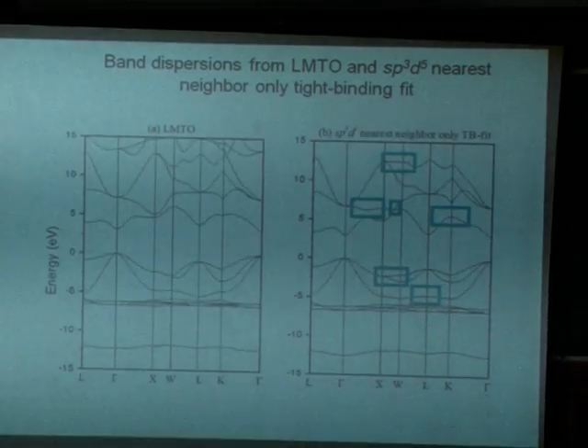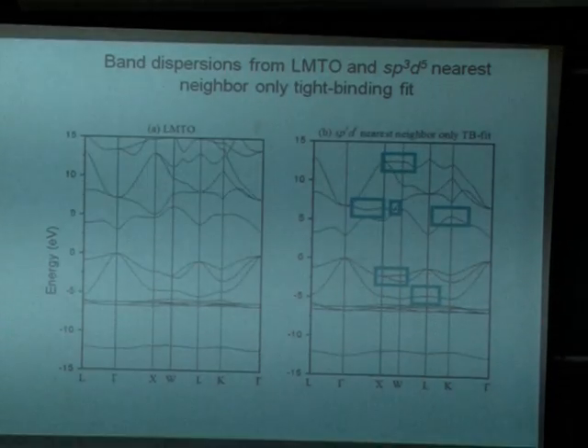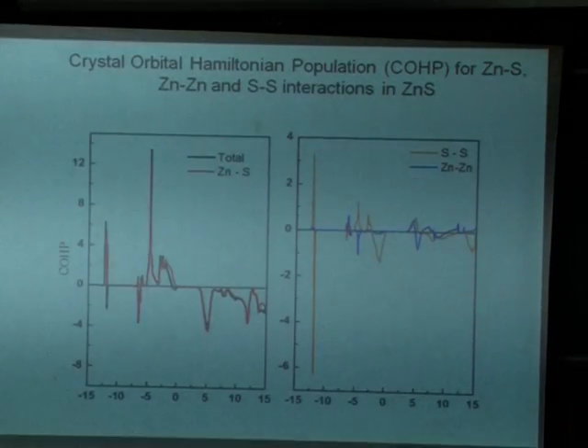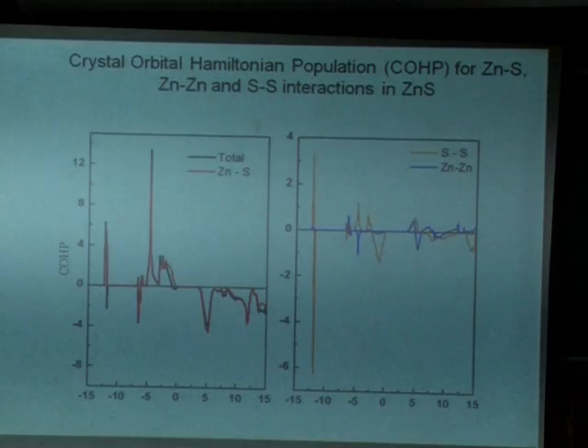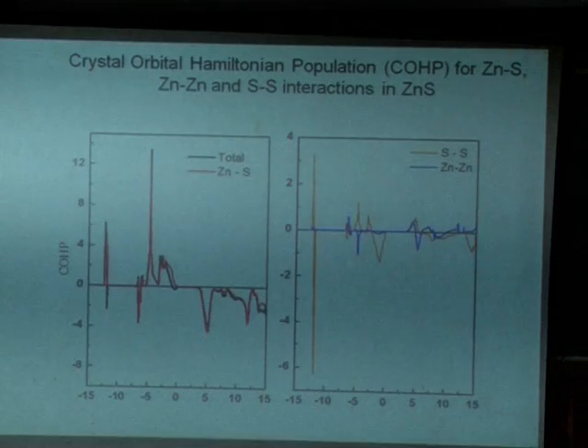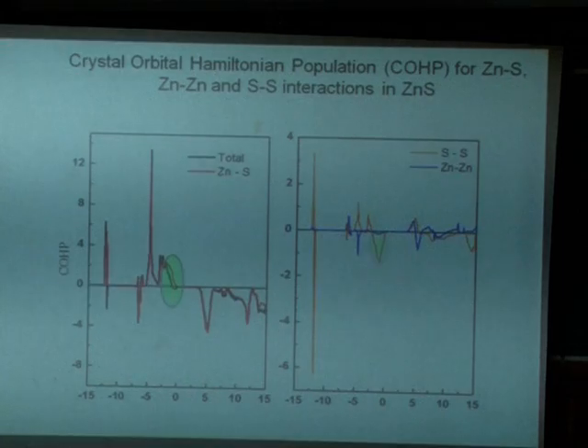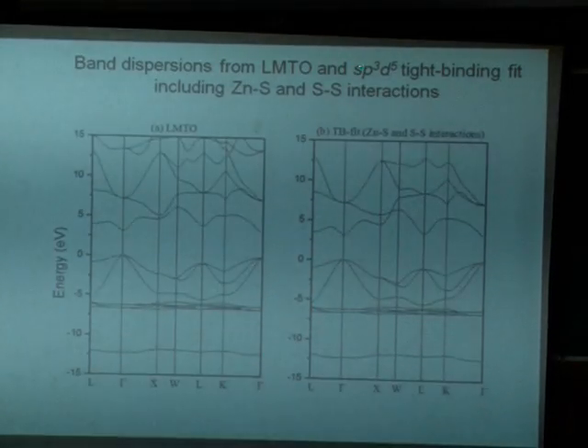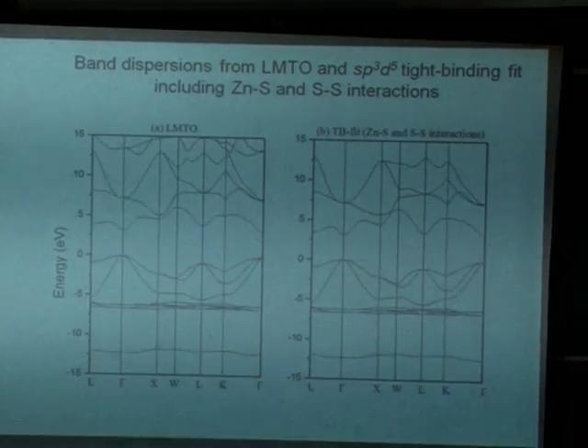So what am I missing? By analyzing it further, we realized what we are missing, and I'll not go into the detail of how we do that, that's in the next transparency. It essentially says that sulfur-sulfur interaction is also very important, because so far we were only doing the nearest neighbor zinc to sulfur and sulfur to zinc hopping. But sulfur to sulfur hopping is also very important. So we expand our model further: sp3d5, zinc and sulfur, and I add in sulfur-sulfur interaction also.